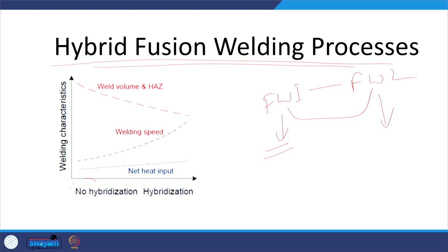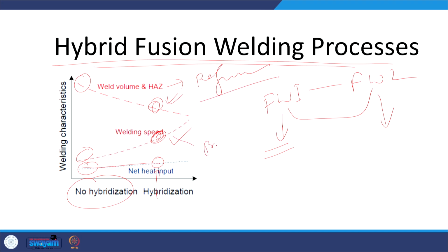Okay. So, if we do not do any kind of hybridization, then our heat input is less, but the welding speed is also less. Our weld volume and heat affected zone are very large. So, all these are undesirable. When we do the hybridization, there is a marginal increase in heat input, but there is a significant increase in the welding speed and significant reduction in the weld volume and the heat affected zone. So, that helps in improving the performance and the productivity of the weld joints.